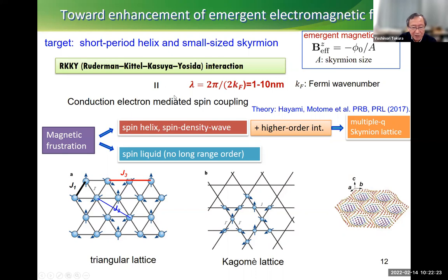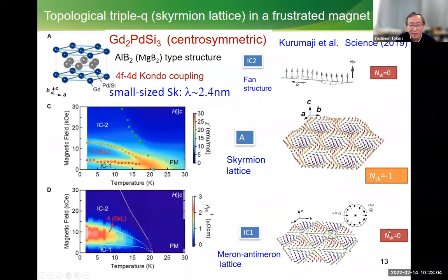So in order to do this, we have a very high symmetry lattice structure, a two-dimensional lattice structure, a triangular lattice or Kagome lattice, and also higher order interactions. According to these kinds of theories, it always stabilizes the skyrmion. And the magnetic frustration sometimes leads to the spin liquid phase. This is another big topic of condensed matter magnetism. But also this kind of spin helix or spin density wave can show up. And if we have a good chance, triple Q or multiple Q structures can cause these very short, small size skyrmion crystals.